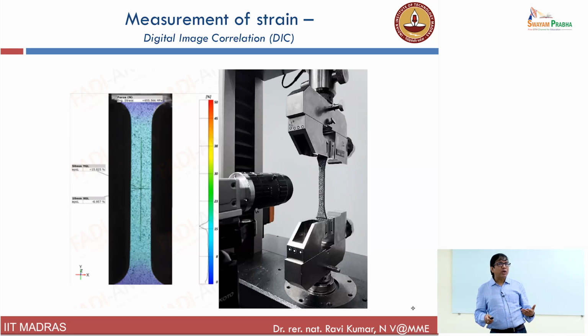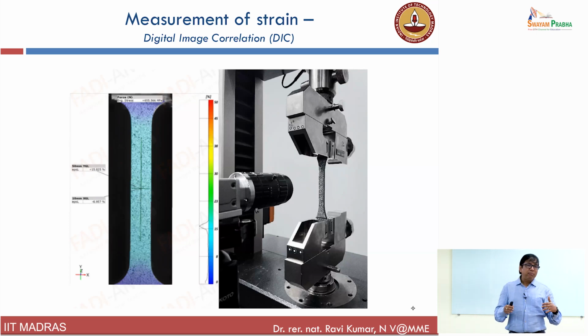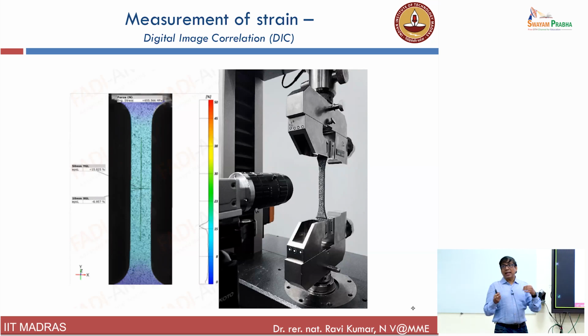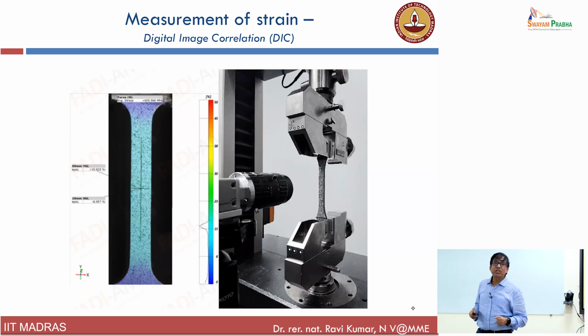So that non-contact mode also helps us to really get away with the strain gauge problem, because what happens with a strain gauge is that it tends to peel off when deformation takes place and so on. So therefore, non-contact mode is a fantastic thing. Again, easy to come and give a lecture, but not so easy, because we have used the digital image correlation technique for ceramic samples, and it is not so easy to capture strain, particularly in the elastic region. So why I'm saying this is that many people think mechanical testing is a very easy thing. It's not easy if you want to get reliable data and credible data. And we have seen, in fact, one of my former students really struggled to get elastic strain, which is extremely small in ceramics, using digital image correlation technique.